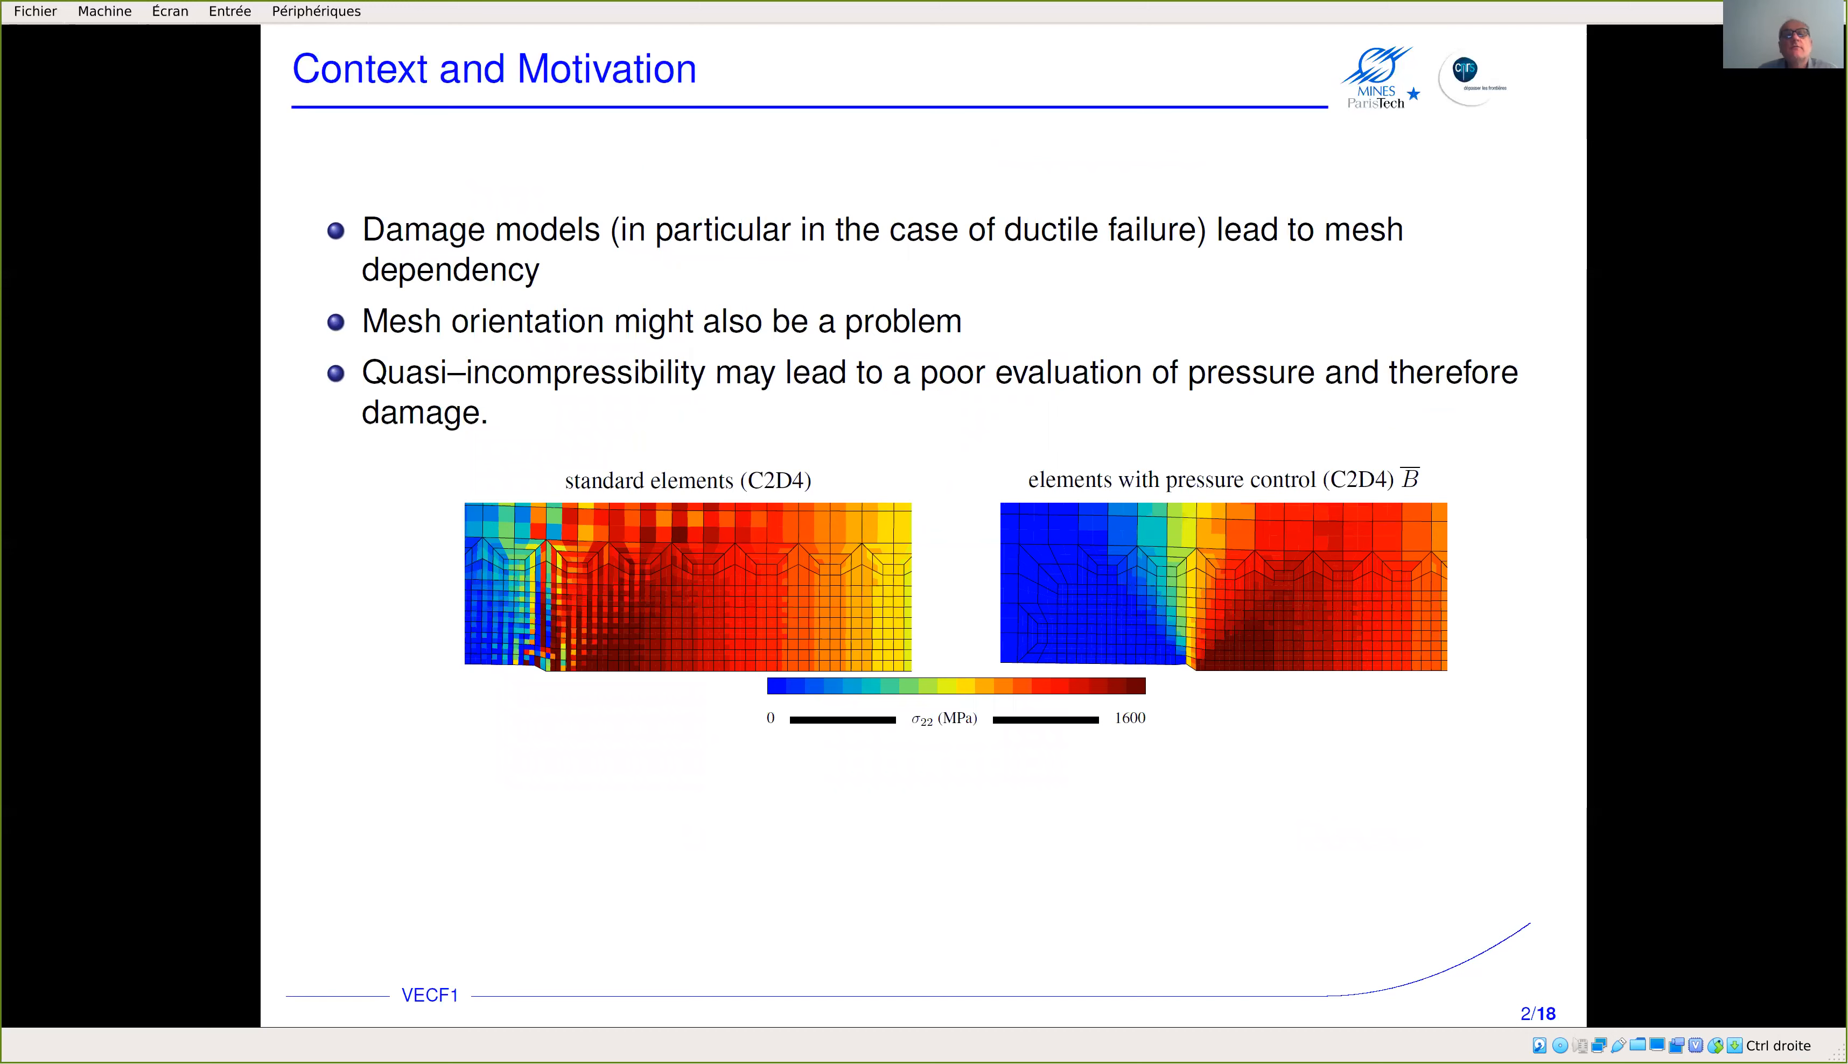There's another problem which we also solve with the model we introduced—the problem of quasi-incompressibility of this material, which will lead to very poor evaluation of pressure and therefore damage, because damage depends on pressure. Here is probably the worst you can do using standard linear elements.